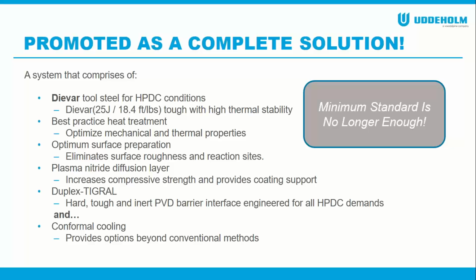You follow that with a duplex Tigral process, which includes a plasma nitriding, a layer of about 1 to 2 thousandths, immediately followed by a PVD film. And this is all done in the same chamber. So an oxide layer is not a factor, as you would get with many other services where nitriding is done separately from the PVD coating.